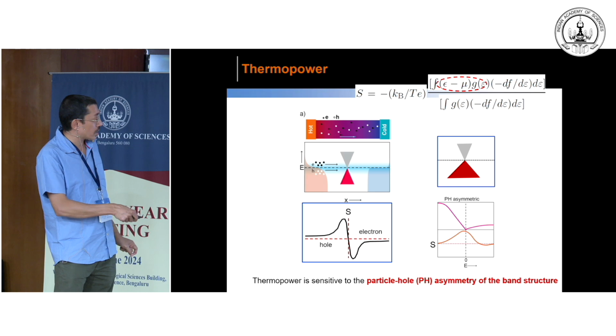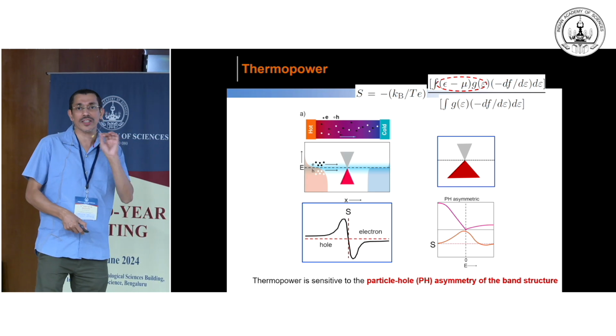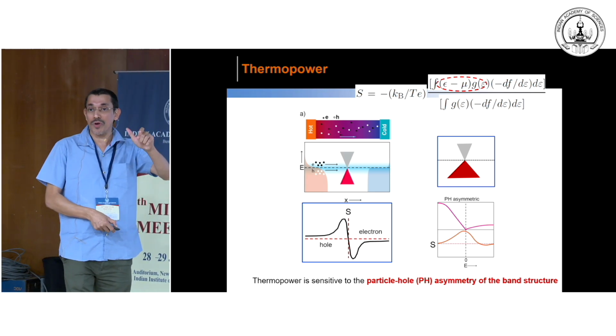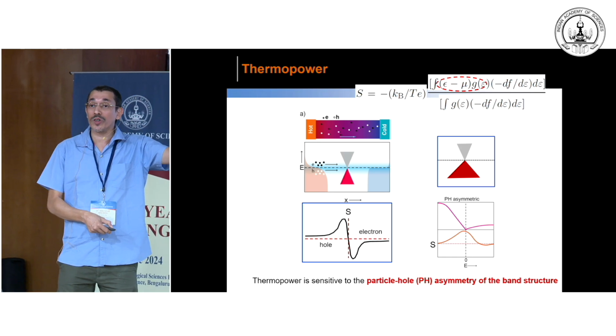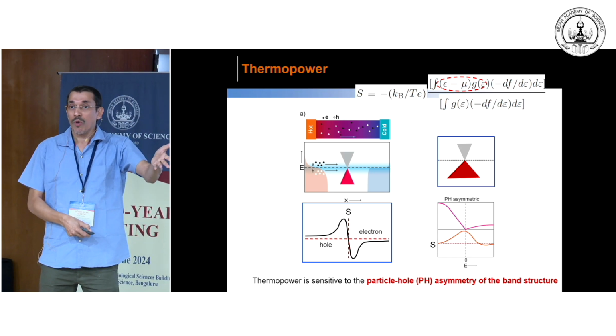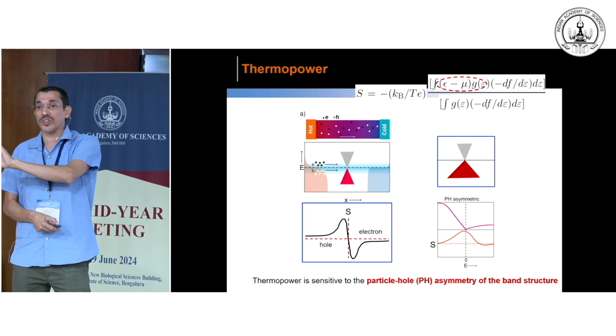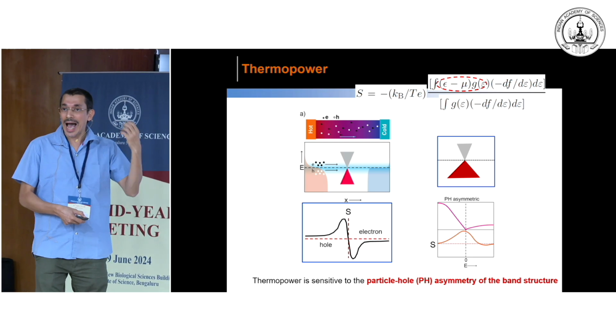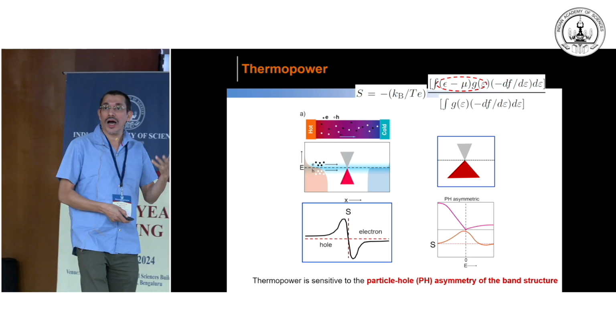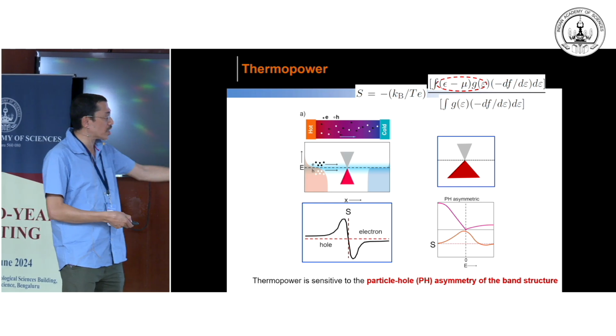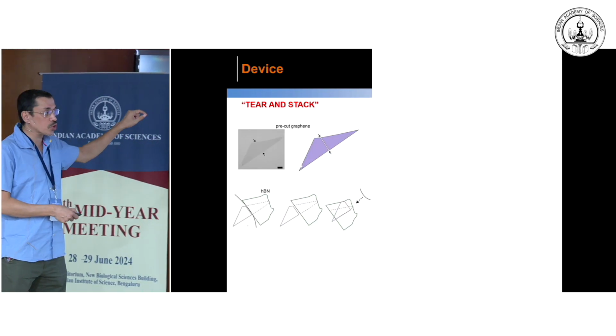So the point is, thermopower is very sensitive to particle-hole symmetry. In other words, thermopower is proportional to the derivative of the density of states, whereas the resistance is just proportional to the density of states. So you can see that thermopower is highly sensitive, so it can give information about your band structure. So that comes to the way we make the devices.